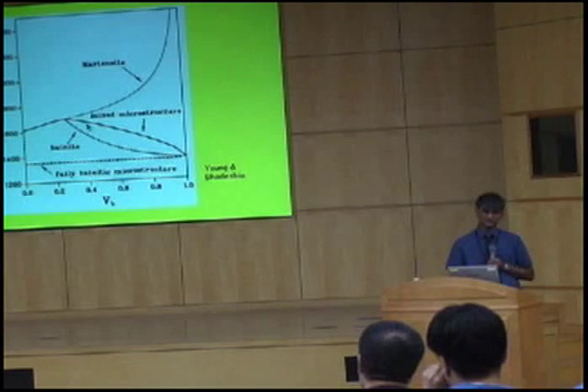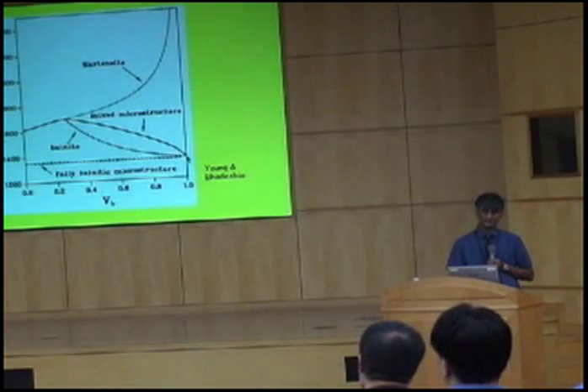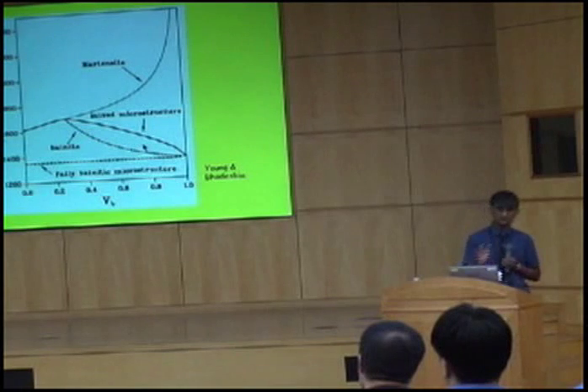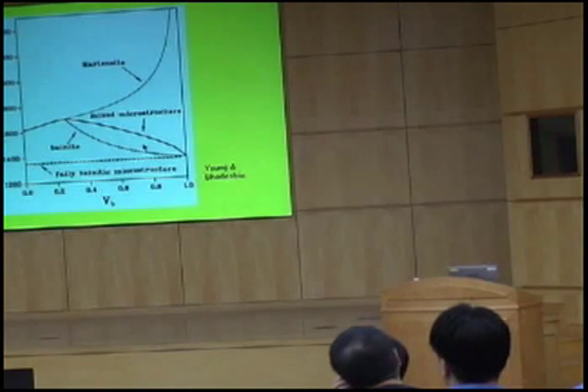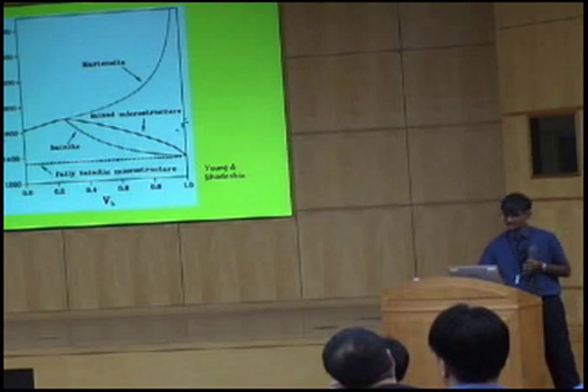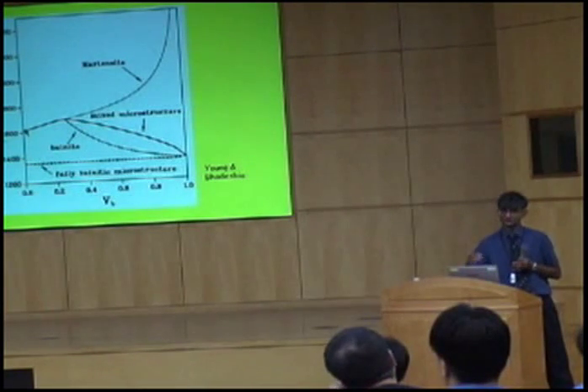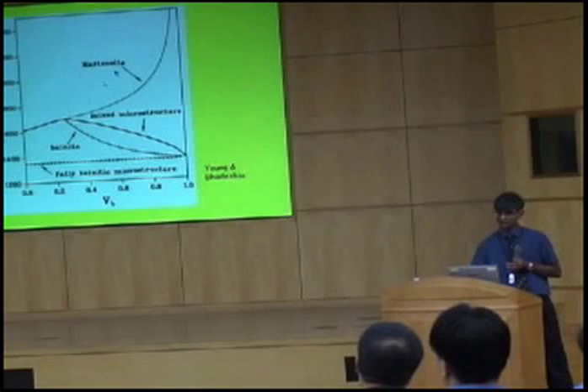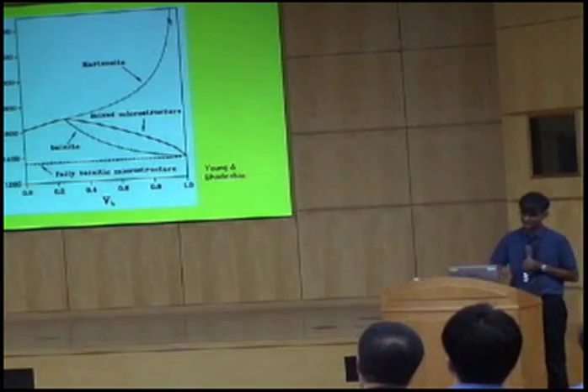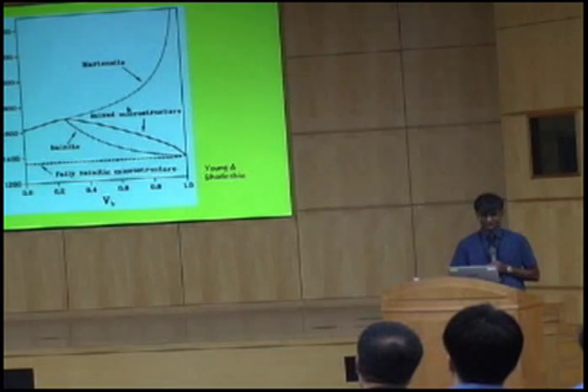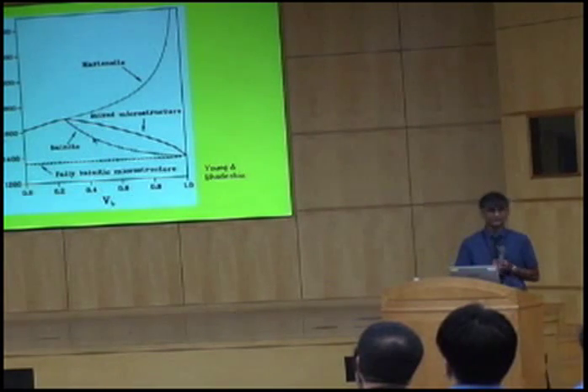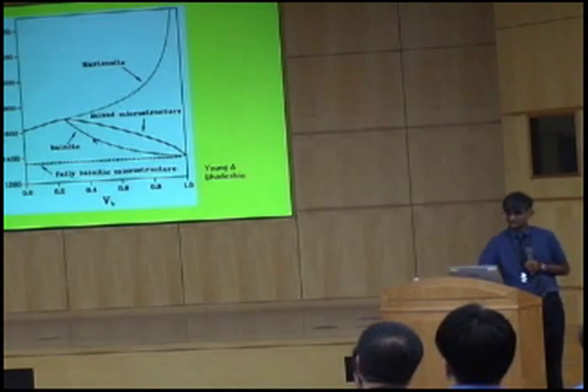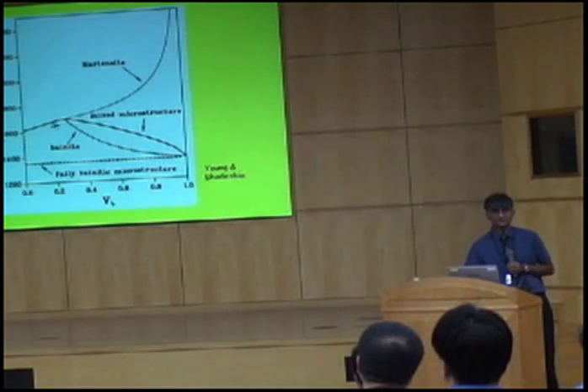And then we have the plastic constraint effect. And you can see that when we do that, we get a peak at a certain volume fraction of bainite. So there are two effects. One is that the strength of martensite itself is not constant because we are putting carbon into the austenite. So here, when we have a large volume fraction of bainite, we expect a very high strength martensite. Okay? So the strength of martensite is not constant. That contributes to the strength of the mixed microstructure. But then we have this plastic constraint which actually increases the strength of bainite. And this is the reason why we get a peak in the strength.